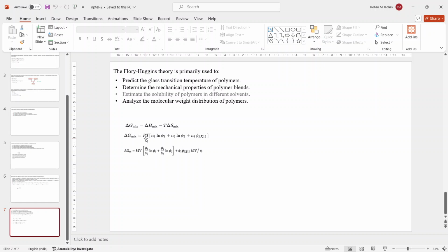Delta G mix is equal to RT times N1 ln phi 1 plus N2 ln phi 2 plus N1 phi 2 xi 1 2. So what are the parameters involved here? Delta G is your change in Gibbs free energy. R is your gas constant. T is the particular temperature at which the polymer and the solvents are mixed together. N1 is the mole fraction of your solvent, and phi 1 is the volume fraction of the solvent. N2 is the mole fraction of the polymer, and phi 2 is the volume fraction of your polymer. And xi 1 2 is the mixing activity parameter for the polymer and the solvent described by 1 and 2.